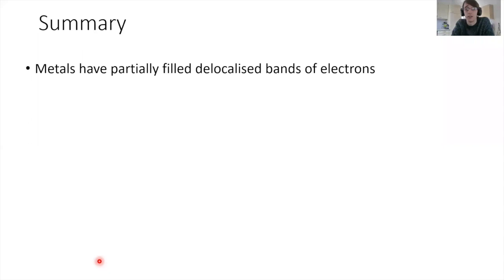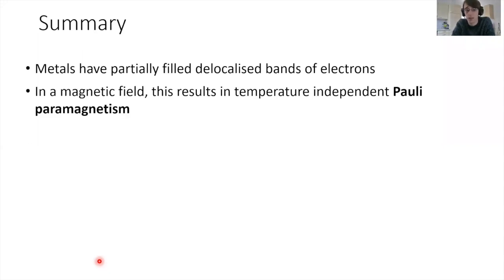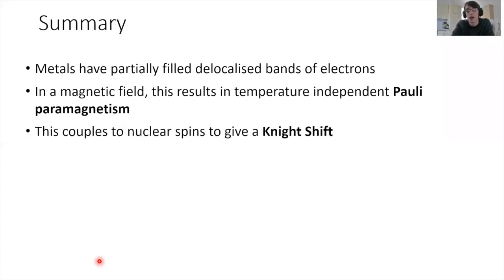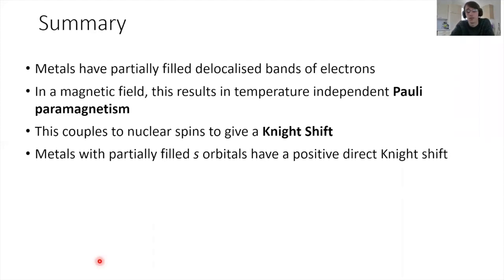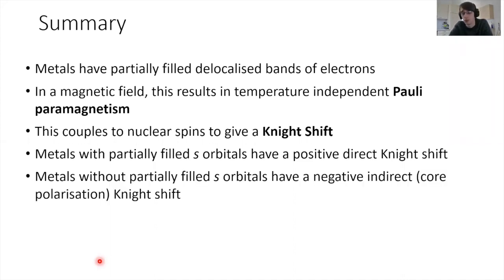Okay, with that, I'd like to summarize the first half of this tutorial. Metals have partially filled, delocalized bands of electrons, and in an applied field, we end up with a net unpaired electron spin density, which augments the applied field, and this is known as Pauli paramagnetism. This is a temperature-independent effect. This can then couple to nuclear spins, and in an NMR spectrum, we see this as a Knight shift. If we have valence s orbitals at the Fermi level, we get a positive shift, a direct Knight shift. But if we don't have s orbitals, we can still get an effect, known as an indirect or core polarization Knight shift, and that is negative.